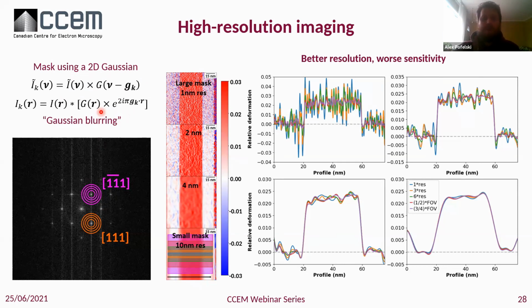And whenever you do a Gaussian blurring, we have the tendency to average the signal in this Gaussian region. Interestingly, when you change the size of the mask, from large mask to small mask, you will see that the noise level is going down. So you will have a better sensitivity with a worse resolution. You can see these are the line profiles taken along this growth direction for different types of averaging profiles: 1 time the resolution, 3 times the resolution, half of the field of view. But the general idea is that you have better resolution, worse sensitivity.